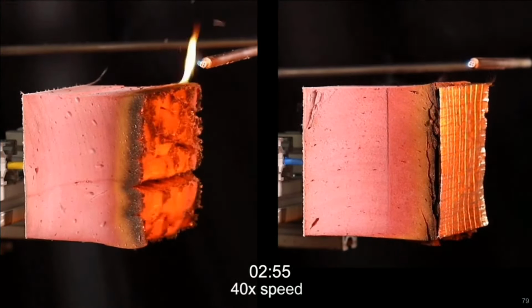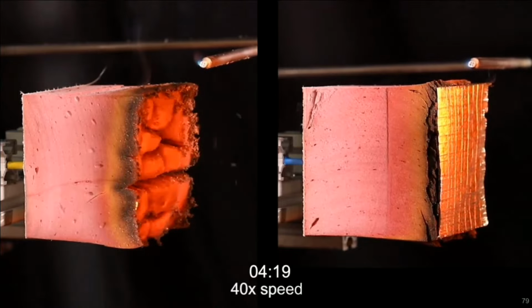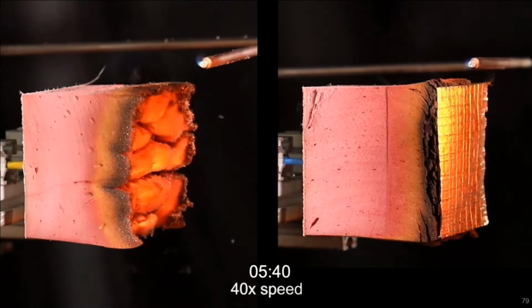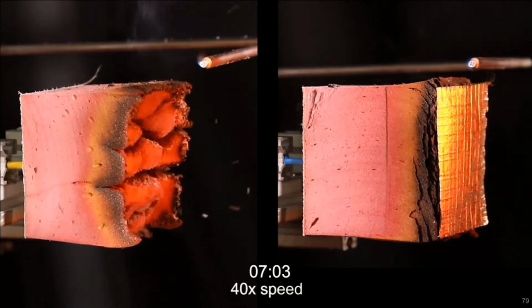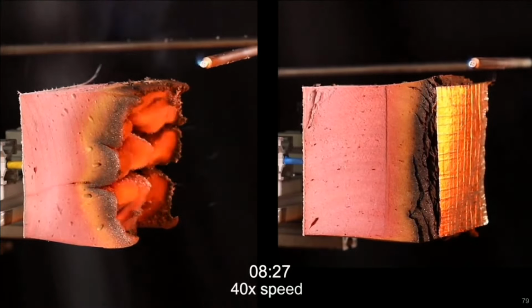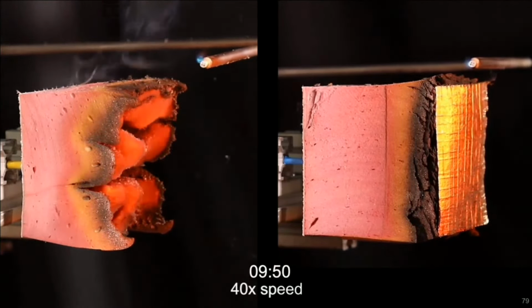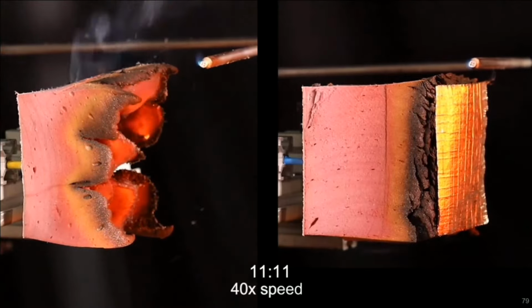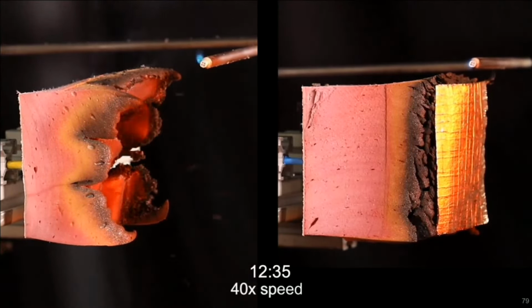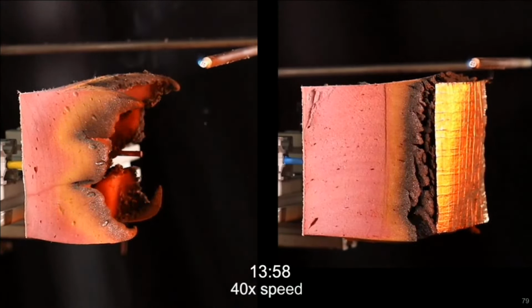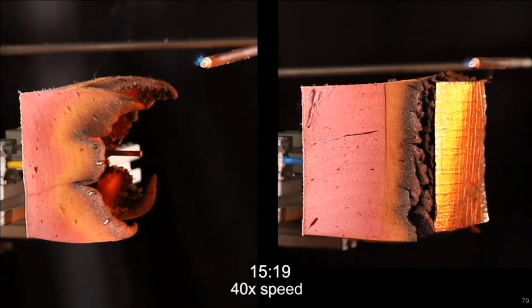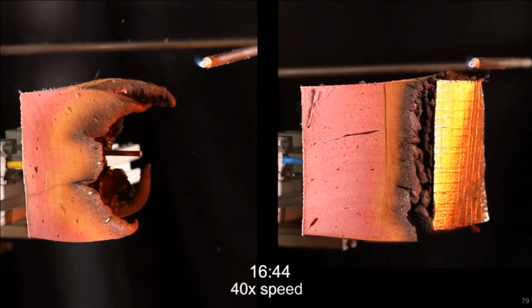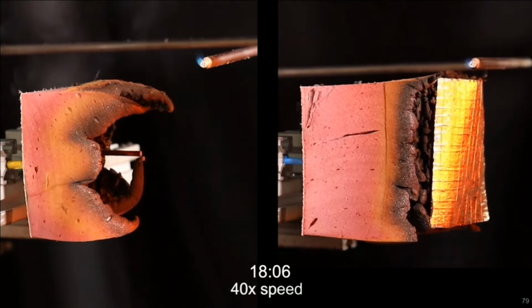The K15 sample, which is protected by a foil facer on the right, does not ignite. The sample without the foil is gradually consumed and continues to smolder throughout this experiment. And this behavior was fairly typical for the Kingspan product. Again, I don't have time to rehearse all of the results from my experiments on both of these materials here. So in a moment, I'll just summarize what I've observed and concluded.